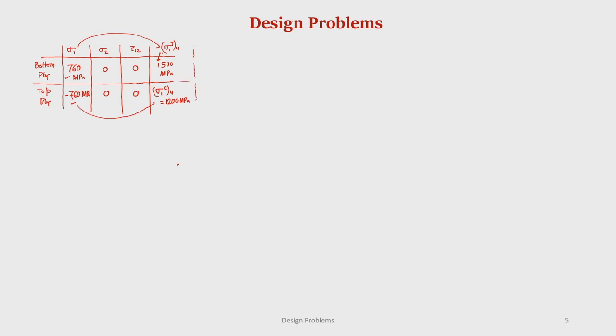Okay, so, what is the strength ratio? It is obvious that because the stress here is much less, so these plies will not fail. Okay. What is the strength ratio? Strength ratio here is roughly 0.5, and here it is 760 by 1200, this is roughly 0.63. Therefore, this is the highest strength ratio. That means, if we keep on increasing the moment, if at all it fails, it will fail here first, but it is far away from the failure, because only when it is 1, it will fail. Now, it is only 0.63.